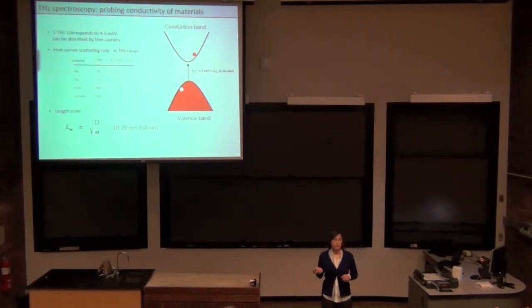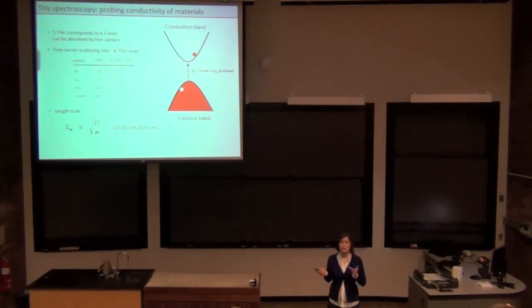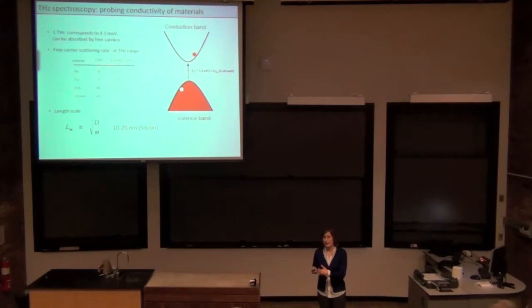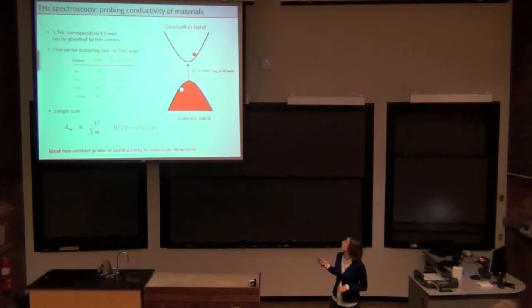The other very important thing about this technique is that we are probing this conductivity on a nanoscale length scale. The length that we are probing is given approximately by the square root of D, which is the diffusion constant, over the frequency. That just tells you how far the carrier can get before the electric field reverses direction. So we're sort of flushing the carriers in. That's how we can probe the conductivity in nanomaterials. So that's when it becomes very important.